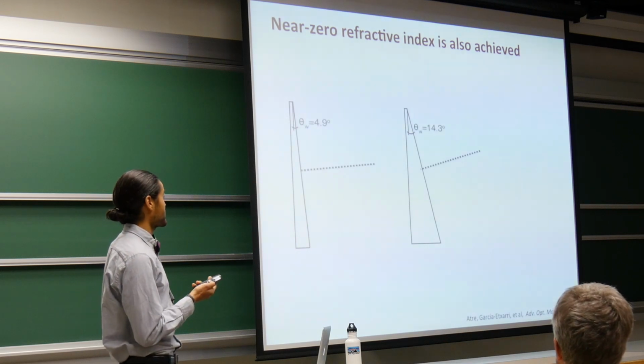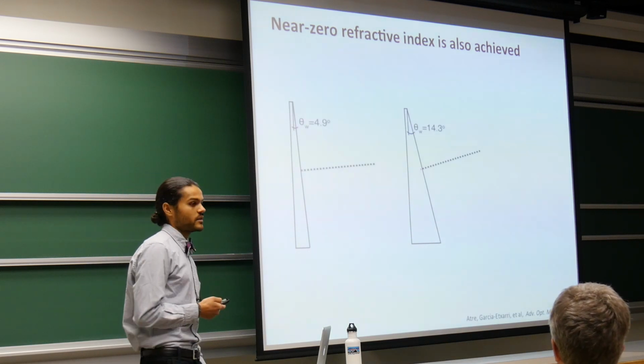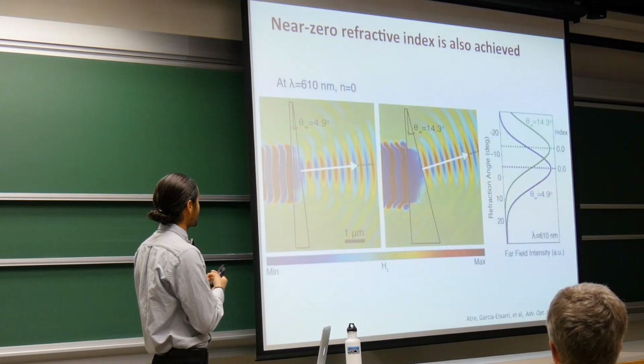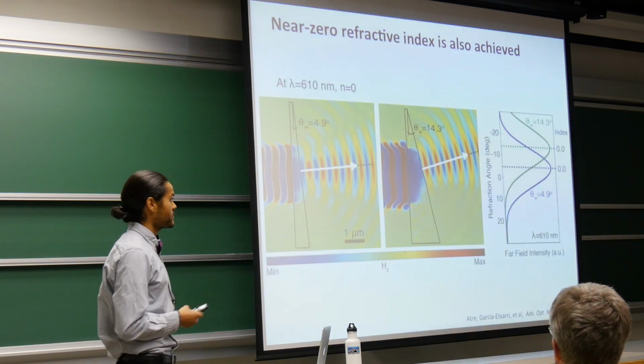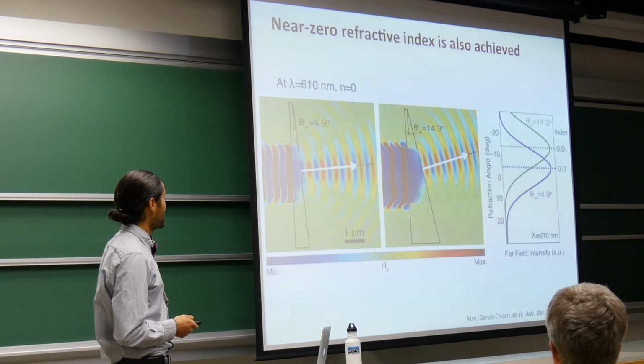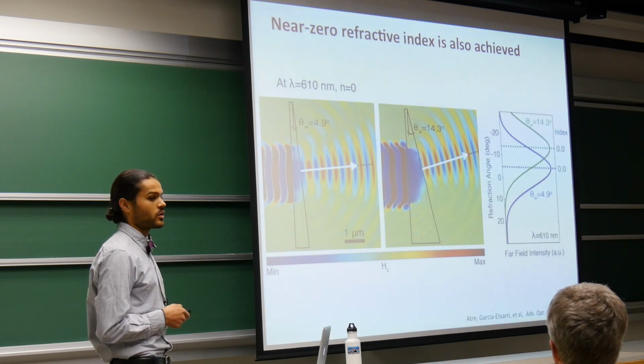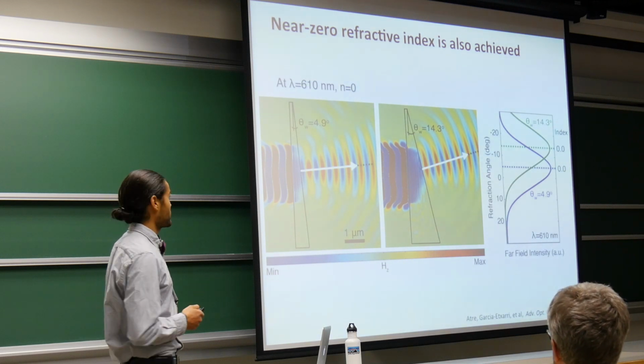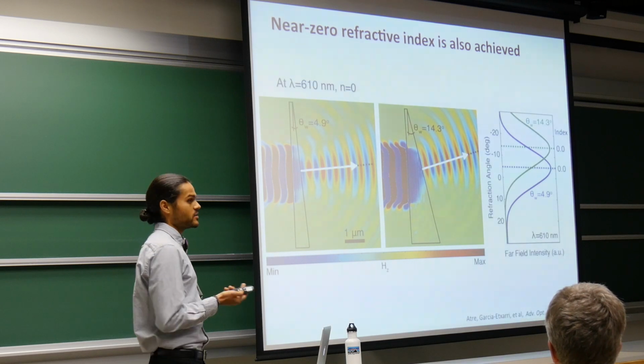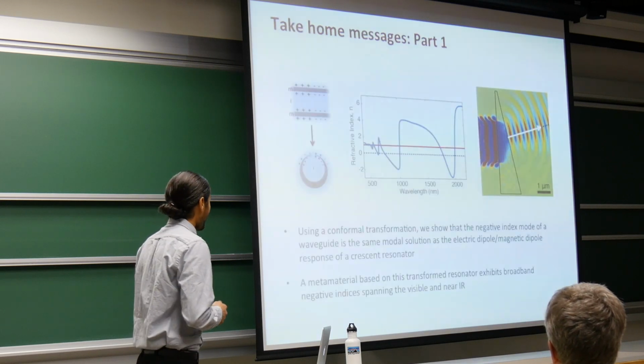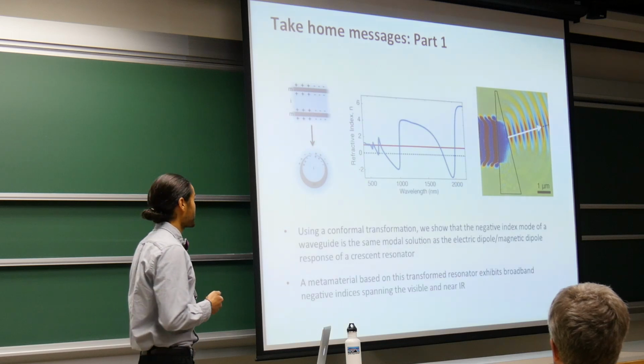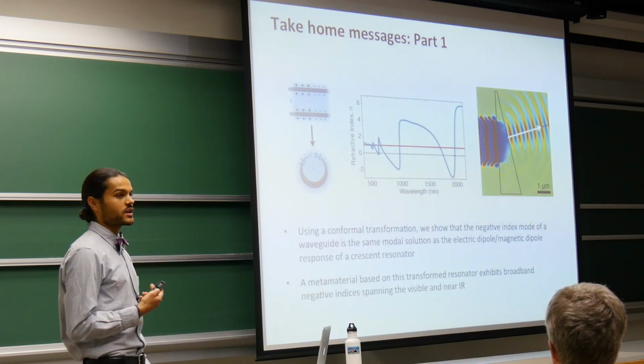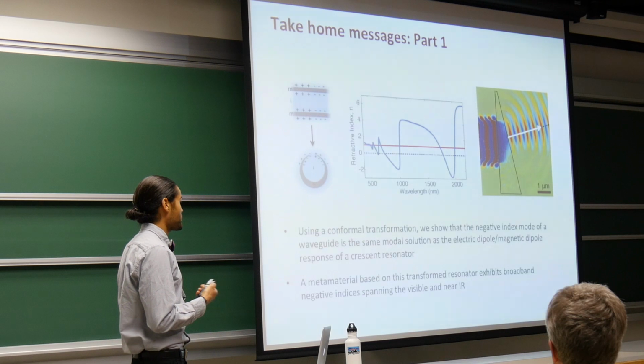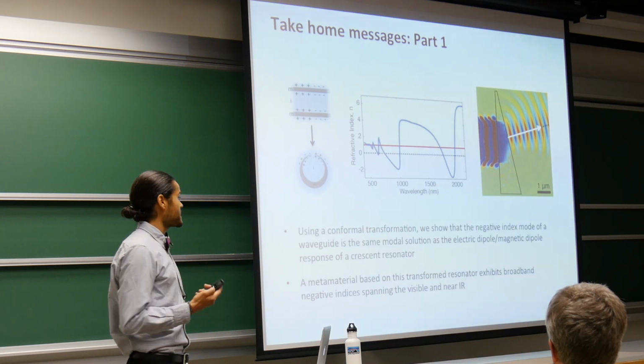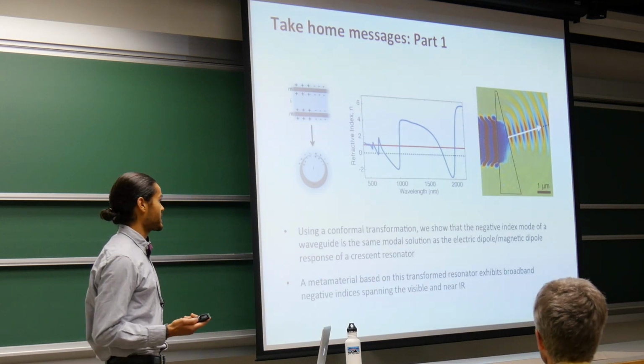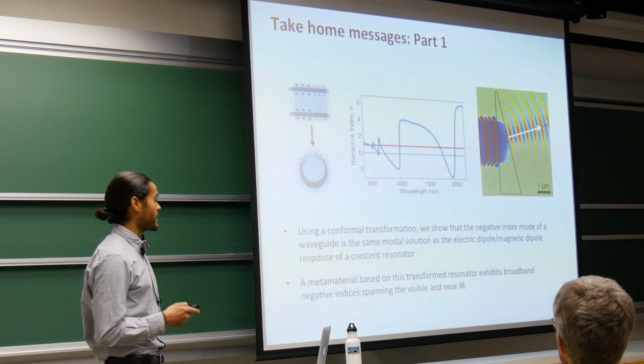And in this case, I'm actually going to just show a wavelength where the index is near 0. And in this case, for both, regardless of the thickness of the wedge or the angle of the wedge, we can see that light propagates along the normal of this wedge, corresponding to that 0 refractive index that we had predicted using the interferometric technique. So to wrap up the first part of my talk, I've showed that we can use conformal transformation to show that the negative index mode of a waveguide is the same modal solution as the electric dipolar and magnetic dipolar response of a crescent resonator.